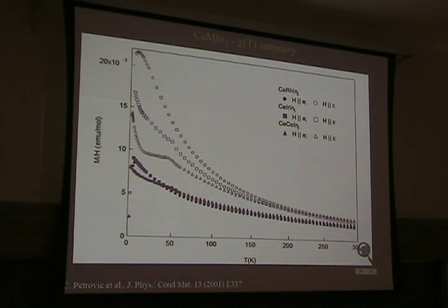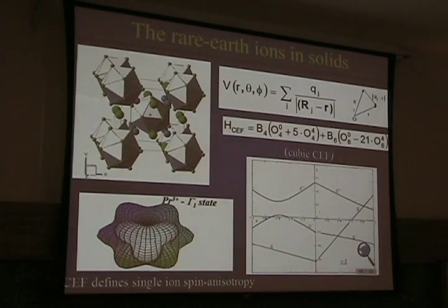Well, we can start thinking of the most simple argument that you can find. That's reasonable, right? So you can look and say, well, in a regular rare earth, where you have no crystal field effect, you put your ion in a lattice, you have the charge, you have the crystal field effects. And that can change the magnetism, right? You're going to split your J multiplet, or you calculate your magnetic susceptibility, that will depend on the energy splittings and the actual wave function you got there.